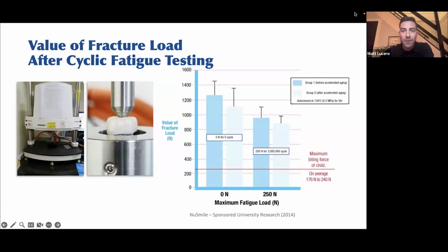You can see they broke them into different groups in this study, where they have one group that was before accelerated aging, which is that darker blue group, and then you have that lighter blue, which is after accelerated aging, where they've run it through an autoclave to kind of mimic an aging process on these crowns. And with 0 newtons for 0 cycles, they put it under heavy pressure, and it would fracture around 1,200 newtons, maybe a little over 1,000 newtons after it's been aged a bit. And then after they put it through 250 newtons for 3 million cycles, it still doesn't fracture until about 1,000 newtons of force.